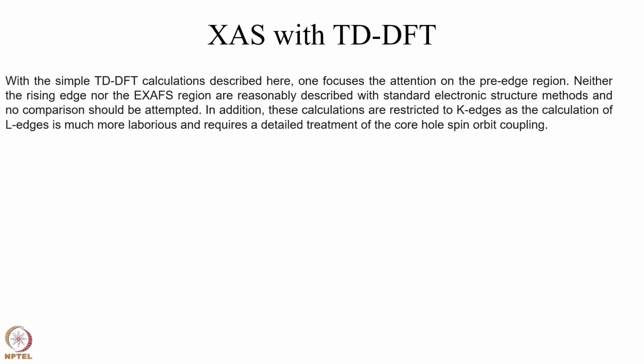With the simple TDDFT calculations described here, one can only focus the attention on the pre-edge. Neither the rising edge nor the EXAFS regions are reasonably described by standard electronic structure methods, and no comparison should be attempted. In addition, these calculations are restricted to K edges, as the calculation of L edges is much more laborious and requires a detailed treatment of core hole spin orbit coupling.